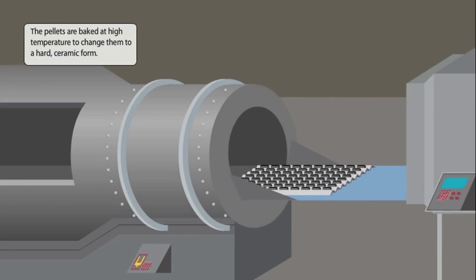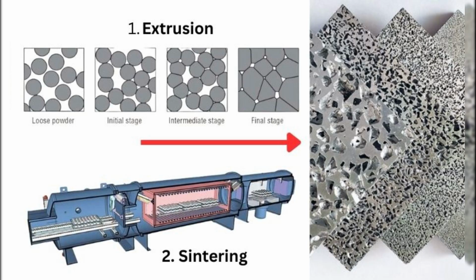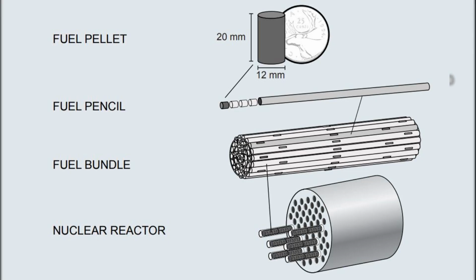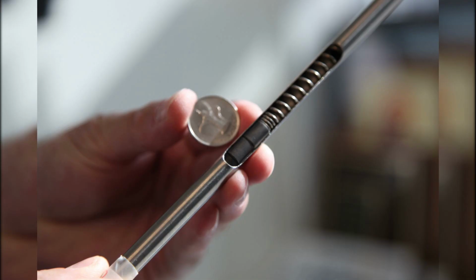To achieve the necessary mechanical strength and density, the pellets undergo a process called sintering. They are heated in specialized furnaces to temperatures above 1700 degrees Celsius in a carefully controlled atmosphere. During sintering, the microscopic particles fuse together, reducing porosity and forming a dense ceramic structure. The pellets shrink slightly during this stage, so the entire process must be precisely calculated to ensure final dimensions fall within strict tolerances. After cooling, each pellet is inspected.